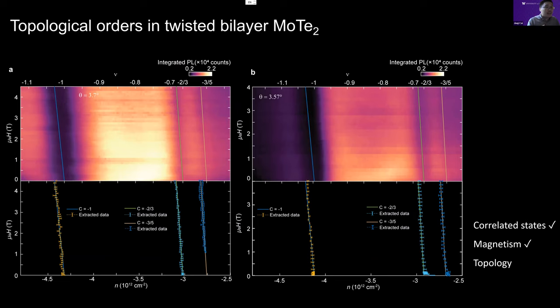What decides the temperature regime in which you can see the phenomena is the band gap, the interaction strength, and also the spin gap, so we need to engineer the states in this moiré superlattice very carefully to raise the temperature. But we already have big progress in raising the temperature from dilution temperature or millikelvin to Kelvin. It's already a two orders of magnitude increase.